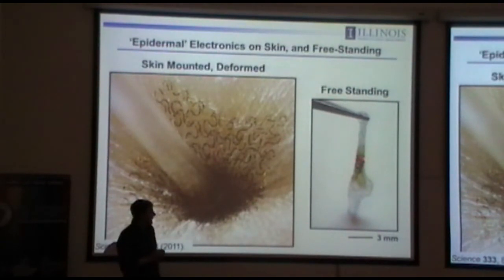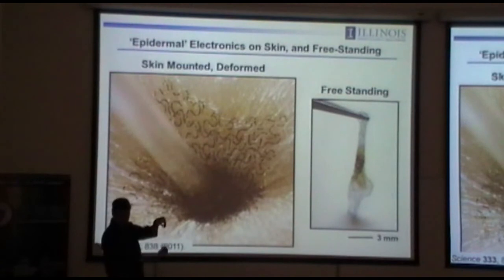And you can see sort of the mechanics here. It's so thin and so low in modulus, it doesn't even support its own weight. It just collapses down on top of itself. And so if you're looking at this, you might wonder, well, how in the heck am I going to hold it to mount it up on the skin in the first place? And that turns out to be really easy.